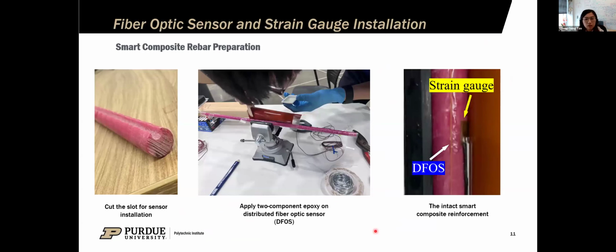So first, we started preparing the smart composite rebar by installing 2 types of sensors, like I just mentioned, the fiber optic sensors and the strain gauges. So the distributed fiber optic sensors can measure the strain along the entire rebar, while the strain gauge can only report the strain data at the points we put the strain gauges. So we install the rebar strain gauges next to the fiber optic sensors so that we can compare the result from the 2 sensors. Since the fiber optic sensor cable is very slim and delicate, we need to have some way to protect the cables.